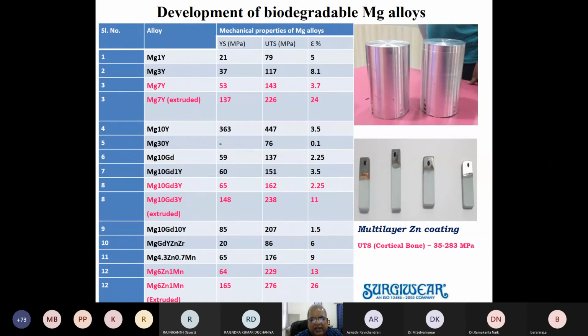And we carried out the mechanical characterization. We have developed some very high strength alloys, right? But presently we are working with the magnesium zinc manganese alloy, which shows a UTS of 276 MPa with 26% elongation. The problem was that again it's corrosion and its very fast degradation rate. The industrial challenge is that after 90-day exposure in the biological environment, your alloy or your implant should have 90% of its strength. After 90 days, it can degrade at any rate it wants. So we have to make it stable and strong for 90 days. So there are reports, now people have reported a number of coatings.